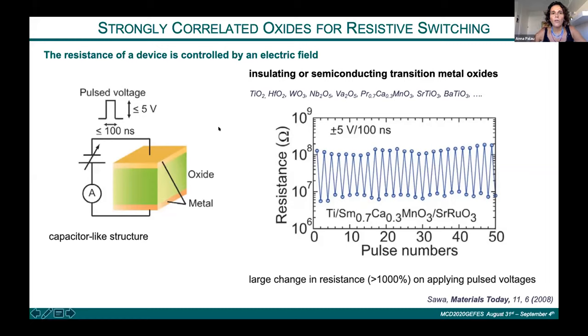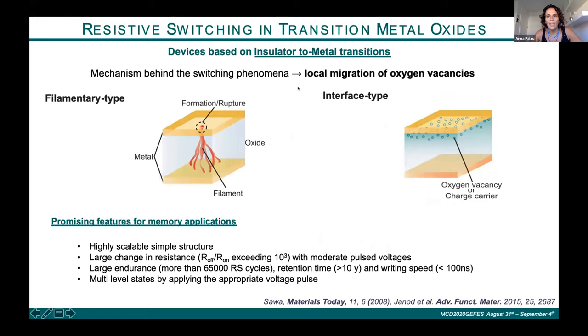In this case, with these strongly correlated oxides, what is mostly used is an insulating or semiconducting transition metal oxide, which is sandwiched between two metallic electrodes. And by applying a voltage pulse, this insulating material behaves as a conductor, decreases the resistance, and then this switch can be performed in a reversible way, inducing very large changes in the resistance. All these systems start from the insulating phase, and the way that they go to the metallic phase is by a mechanism which is very localized, by forming a filament, which is induced in the material and produces a conductance through the two gates, or by modifying a very thin layer below the contact. It's an interfacial type of change.